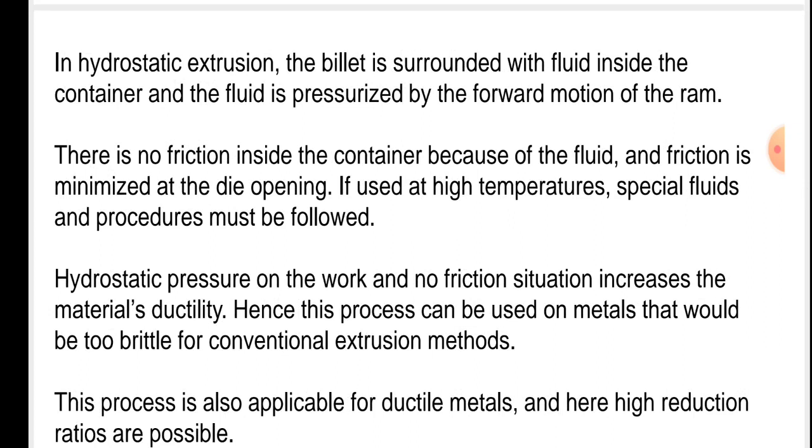In hydrostatic extrusion, the billet is surrounded by fluid inside the container, and the fluid is pressurized by the forward motion of the ram. There is no friction inside the container because of the fluid. Friction is minimized at the die opening. If used at high temperatures, special fluids or procedures must be followed.